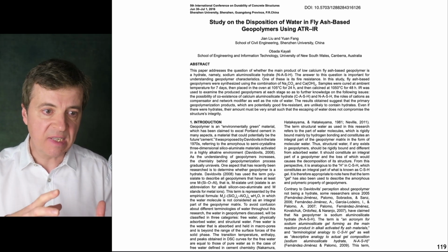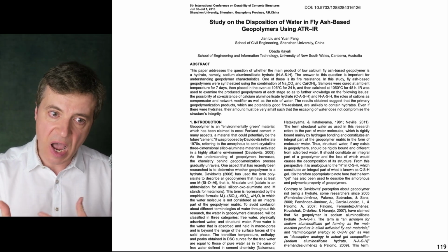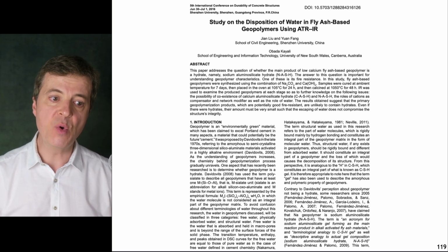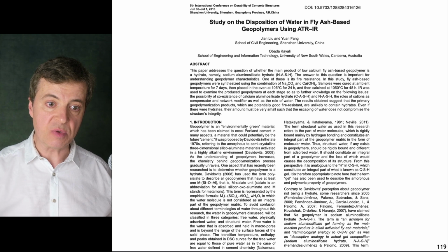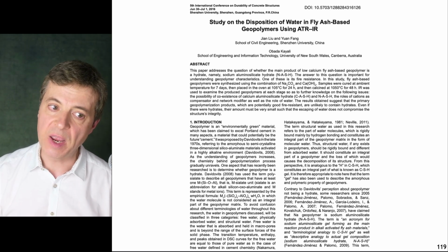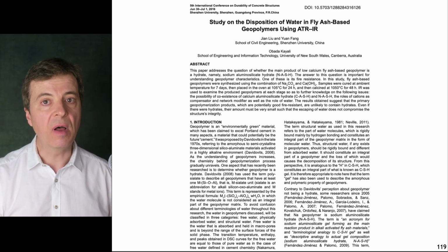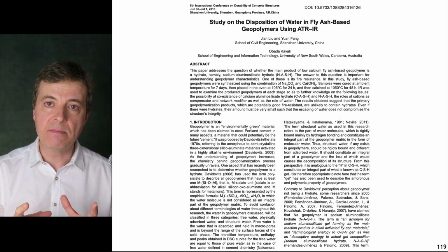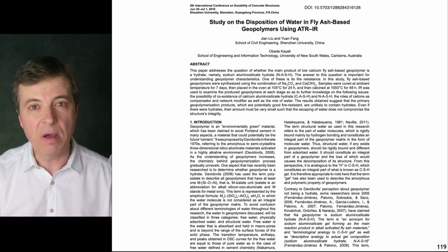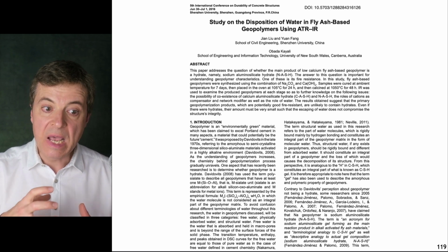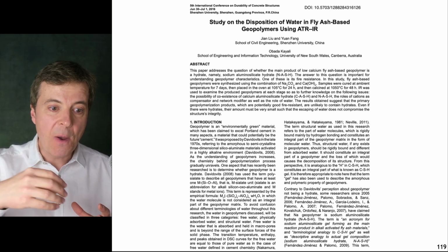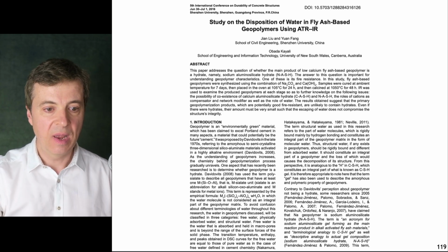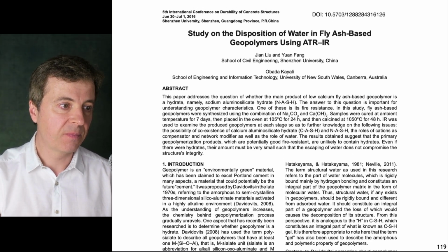If the water exists in the form of a hydrate and contributes to the structure of the material, it should explode when exposed to fire. However, if the water is present as free water, meaning it is not in a hydrate form, steam can escape without causing damage to the structure. Let's read the abstract.